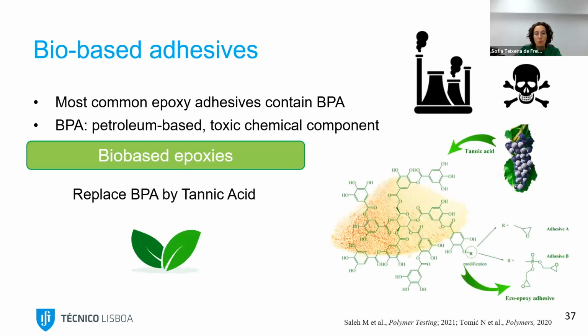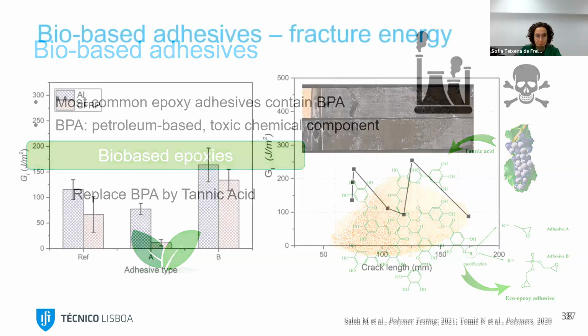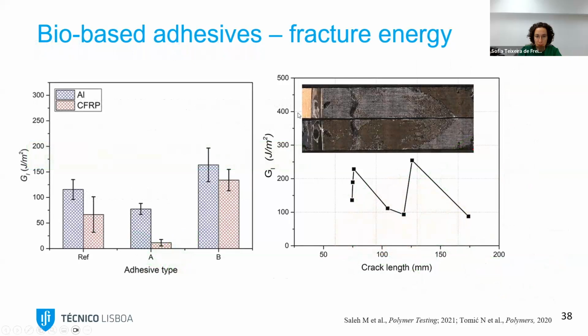So what we did was try to replace the BPA by tannic acid. Tannic acid is a component that is bio-based, coming from, for example, grapes. And we tried to see what the consequences were of replacing this BPA by tannic acid. We performed the same type of tests, the DCB, with aluminium and CFRP. And here is an example of the energy release rate against the crack length and the fracture surface.